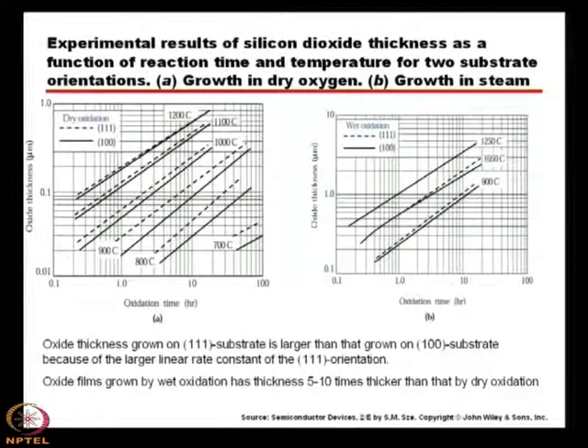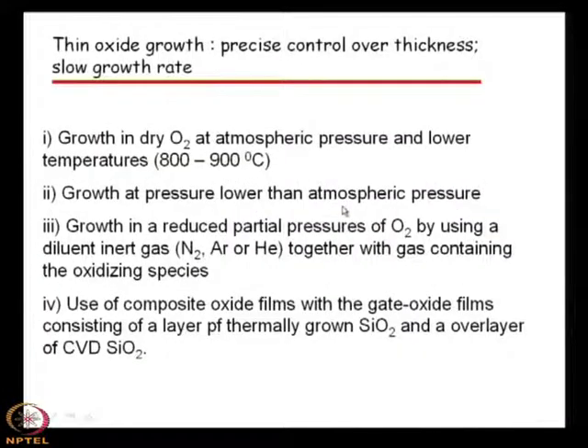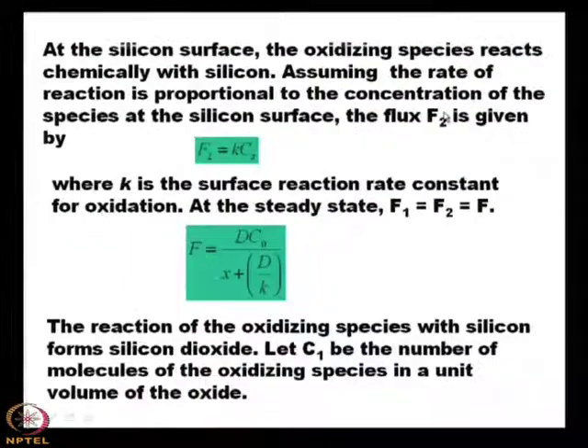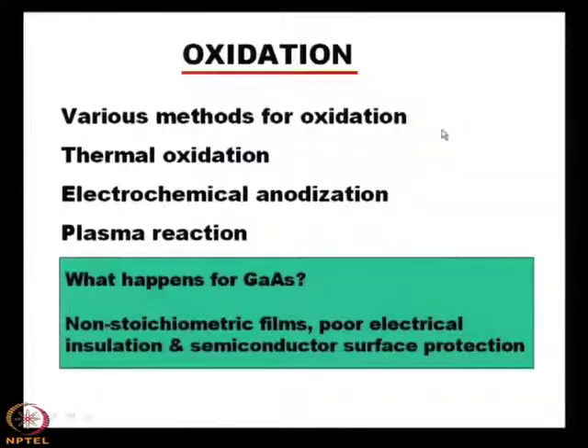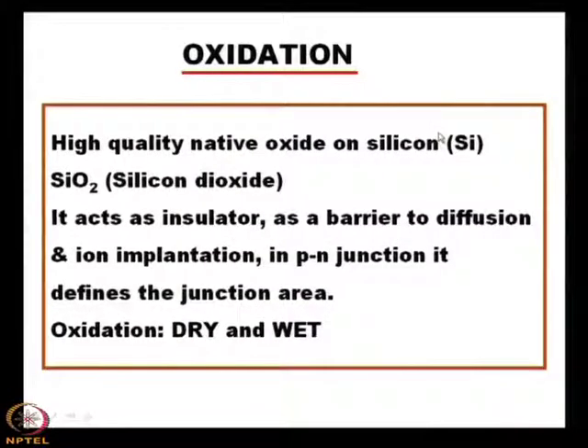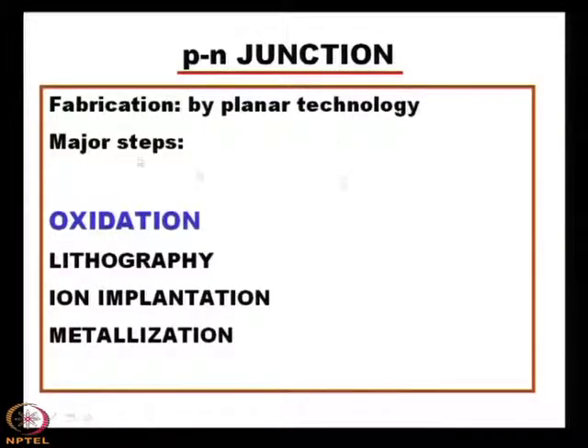Another important thing from these studies is that to grow thin oxide and to make precise control over thickness, slow growth rate is important. Slow growth rate is important where one can precisely control the thickness, because one can see that in process technology, when we talk about oxidation, it is one of the process steps of planar technology, and we can see that oxidation is the first one, along with lithography, ion implantation, metallization, etc.